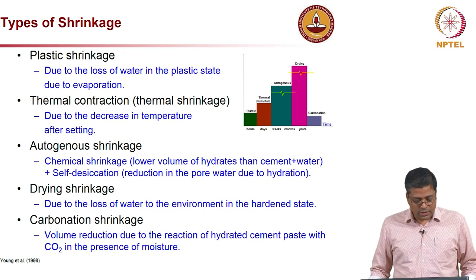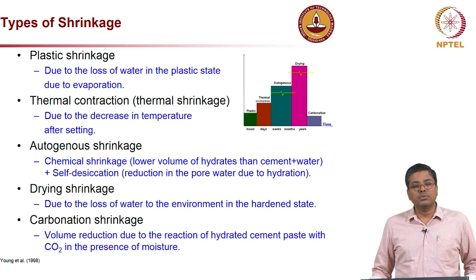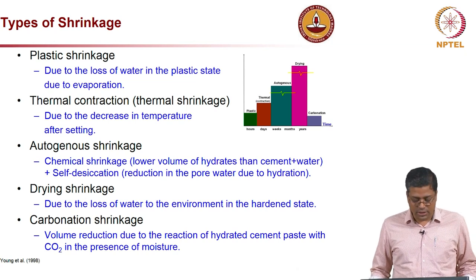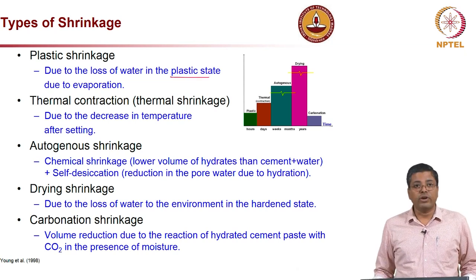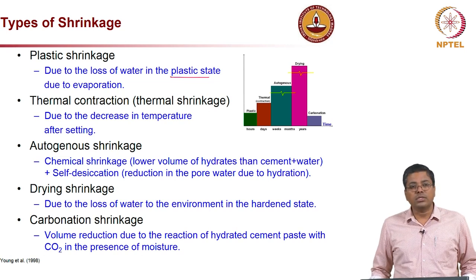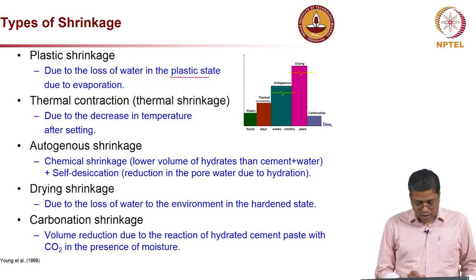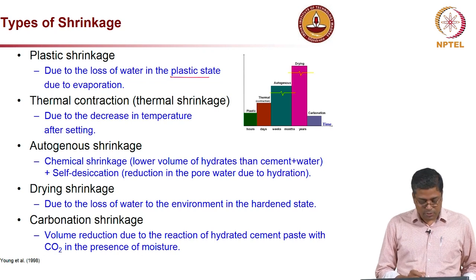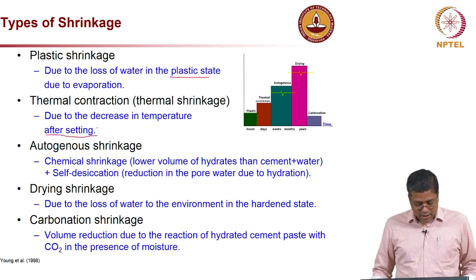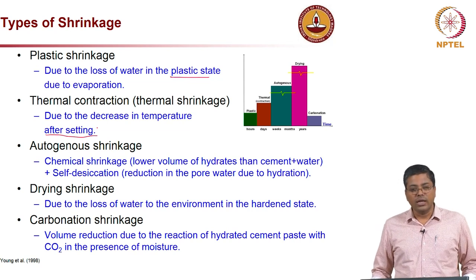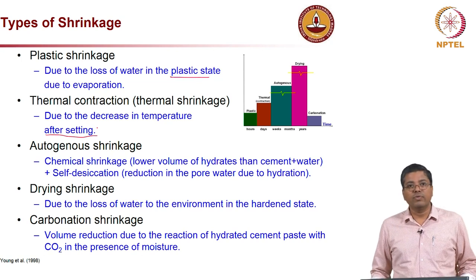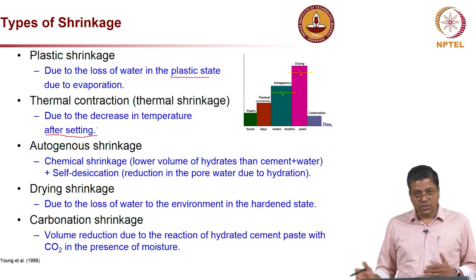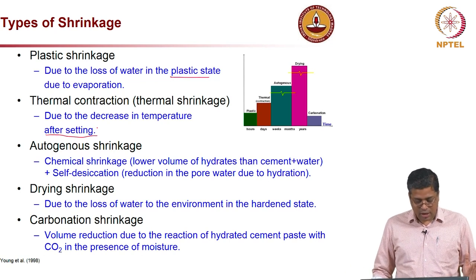Now, what is the cause for these 5 types? Plastic shrinkage is mainly happening because of the loss of water when the concrete is still in plastic state. That means it is still fresh concrete. And thermal contraction or thermal shrinkage happens when there is a decrease in temperature, especially after the setting. And autogenous shrinkage is mainly because of the chemical shrinkage and the self desiccation, which could happen in the first few weeks, from days to weeks.